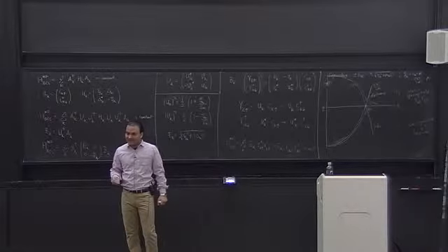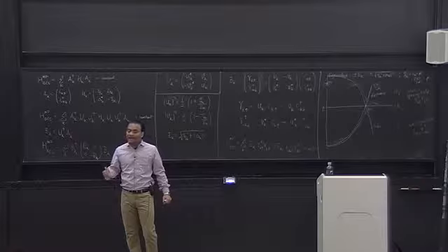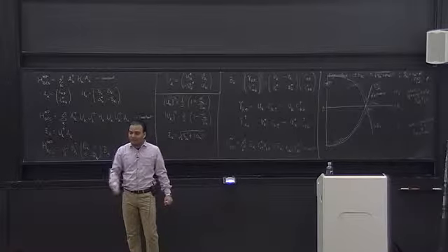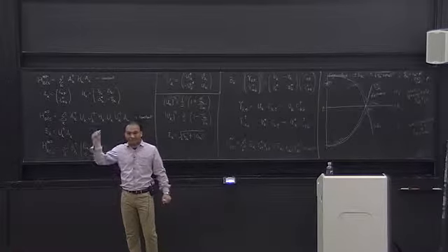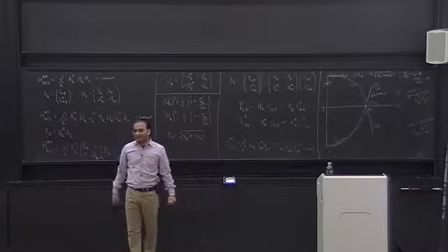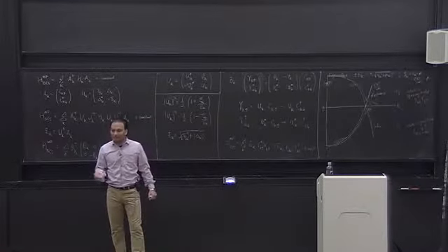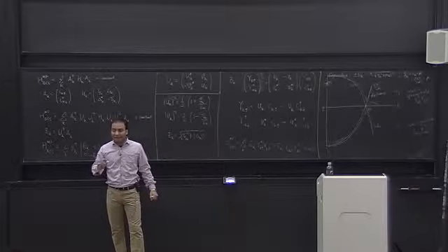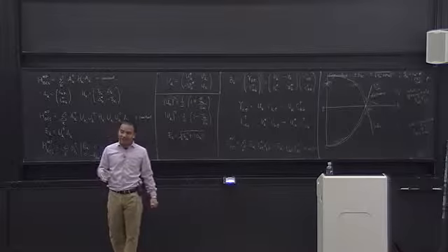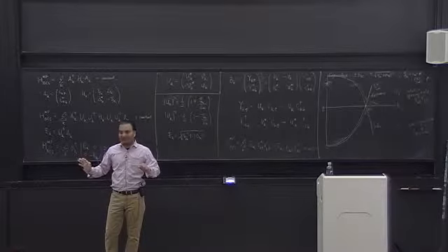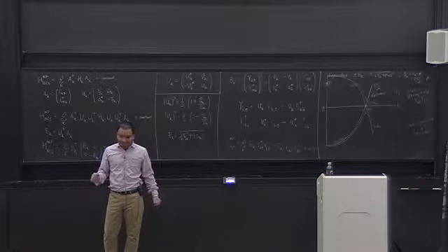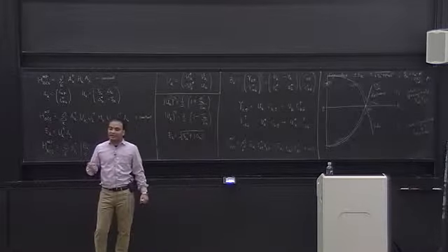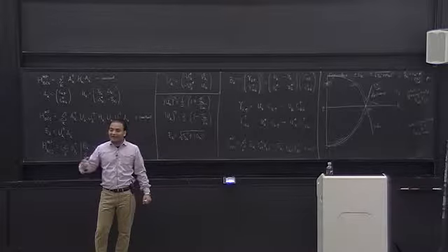So it consists of a lot of terms, and these are a term with no Cooper pair, with 1 Cooper pair, with 2 Cooper pairs, 3 Cooper pairs, and infinite Cooper pairs. This is really the ground state of the superconductor. The BCS Hamiltonian also does not commute with the number operator. So in this state, already you can see that the number of particles is not conserved, right? So that means you can always add or remove particles at will.